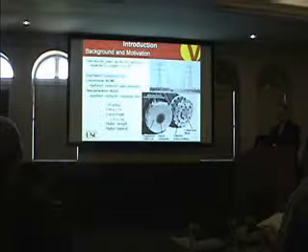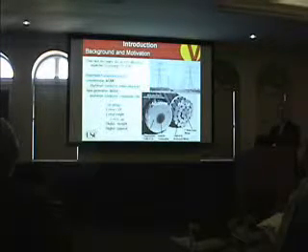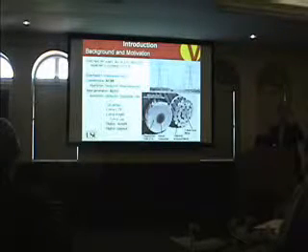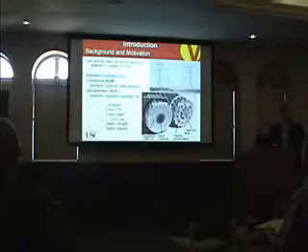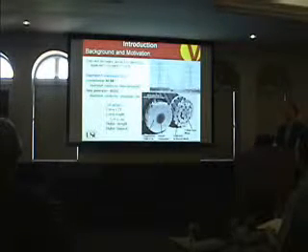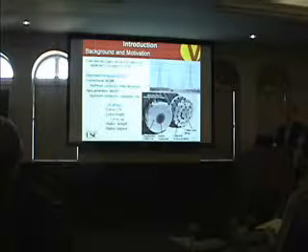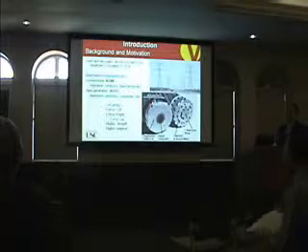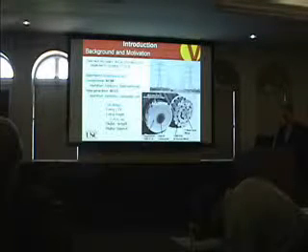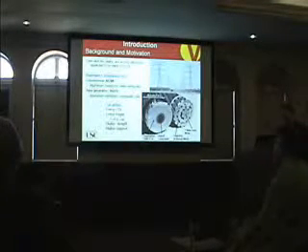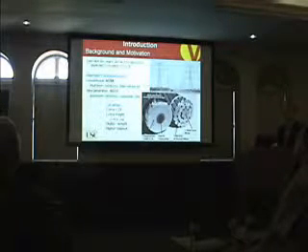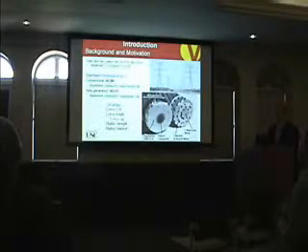It changes over time as the material changes, and also with depth, because at the first layer you have fully oxidized material, then less oxidized, and then intact material. So the diffusivity of these layers is completely different, but how to measure them is really hard. So you're basically using an average diffusivity. Average diffusivity.